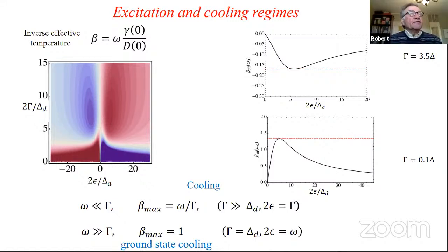Could we understand why this fluctuation becomes very big if the gap becomes super? No, for example, look, if you have only diffusion, consider you have a random force which acts on your oscillator, and you don't have damping. You have some diffusion. I physically ask the question: I would like to see how superconductivity affects heating or cooling qualitatively. And I take a limiting case when superconductivity is very strong, the gap is very strong, Josephson coupling is very strong. Now we have big fluctuation of mechanical vibrations, quantum fluctuations, very big.